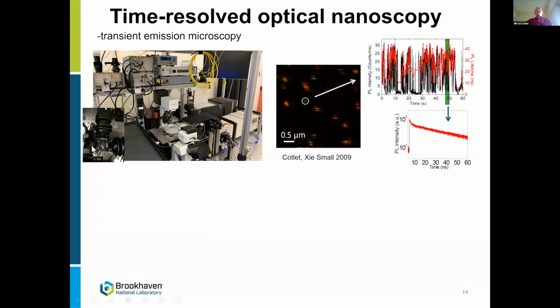So on this instrument, we basically acquire this kind of images. These are isolated quantum dots that are imaged through their emission fluorescence, and then we probe each isolated quantum dot. We can monitor the emission intensity. This is a time scale of microseconds to seconds that we can address here. And also, since we do time-resolved measurements, we can access faster time scales in the picosecond to nanosecond range. So this information is very useful in deciding the type of interaction, the rate for a particular interaction of these nanomaterials.